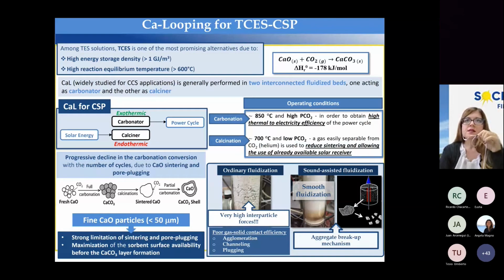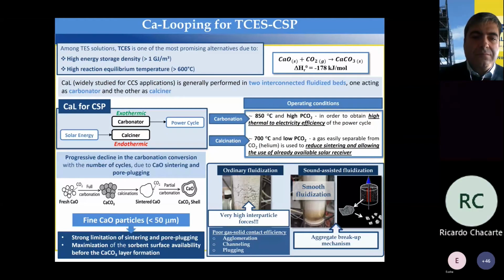In this framework, one of the main drawbacks of the calcium looping system is the progressive decline in the carbonation conversion with the number of cycles, which is due to the calcium oxide deactivation caused by sintering and pore plugging. A possible solution, which has been receiving increasing interest, is the use of fine particles. Besides these, it should be considered that fine particles can provide better gas-solid contact efficiency due to the higher surface to volume ratio with respect to coarser particles, which positively affects the first fast initial phase of carbonation, prior to the slow one.